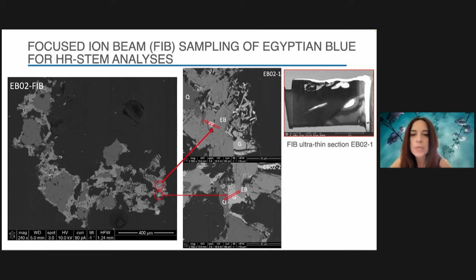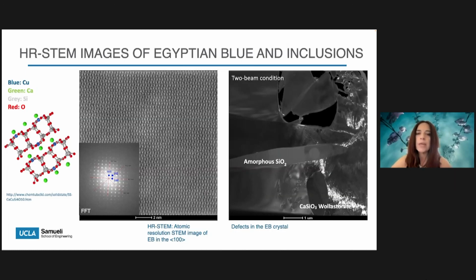To the left and center images, you see the areas sampled with the FIB cuts marked with red rectangles, and to the right, you see one of the ultra-thin slices taken by FIB that includes the different crystalline and amorphous phases. So using STEM, we were able to visualize and verify the crystal structure of Egyptian blue and also identify other byproducts resulting from the processing of the pigment. To the left here, you can see an atomic resolution STEM image of a blue single crystal in the 100 orientation, showing the ordered crystalline structure characteristic of the calcium copper tetrasilicate phase.